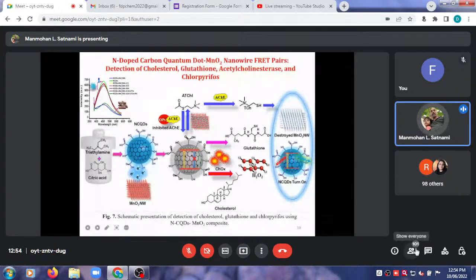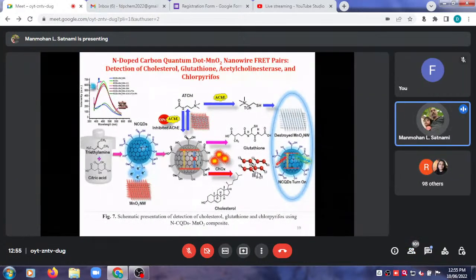Okay, in another route, what we did, we used this quenched carbon quantum dot, which is quenched through the MnO2. We added glutathione. So what will happen? Glutathione will reduce MnO2 again, and it will form Mn2+ ion, and this glutathione will dimerize. Then fluorescence intensity of carbon quantum dot will again recover. In another route 3, okay, so what we did actually, we used the same carbon quantum dot MnO2 to determine the glutathione, the activity of acetylcholine esterase, and pesticides.